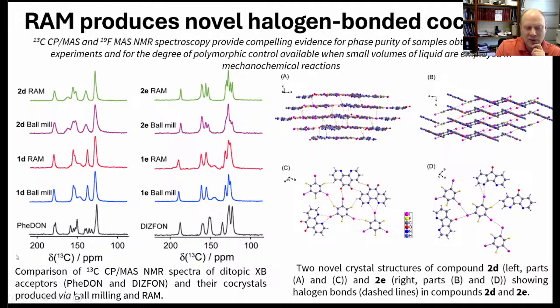So again, a few more examples here of carbon-13 spectra. Again, at the top right here, 2E, another nice example where we get the same product with ball milling, but clearly better spectral resolution in the RAM product, indicative of higher crystallinity. And again, on the right here, once we've prepared these mechanochemically, we see if we can grow single crystals that reproduce the diffractograms and the NMR spectra. Sometimes we can, sometimes we can't, but nevertheless, it's interesting to look at the halogen bonded networks in these systems.